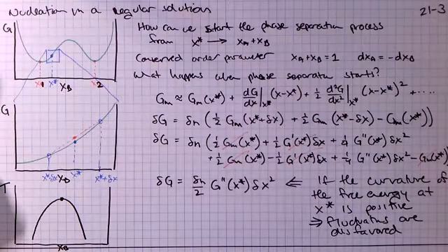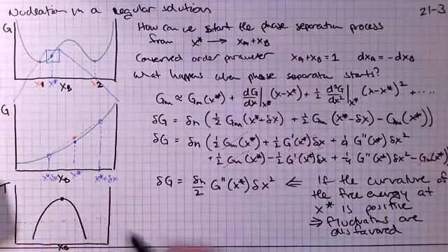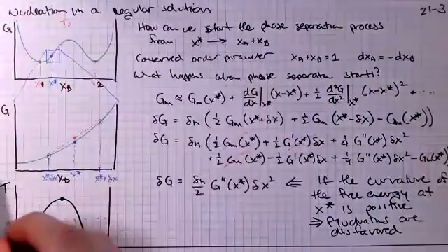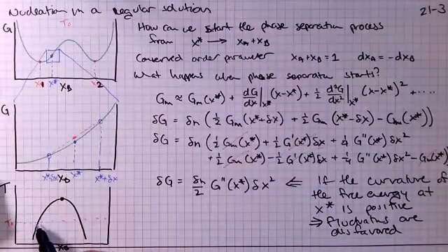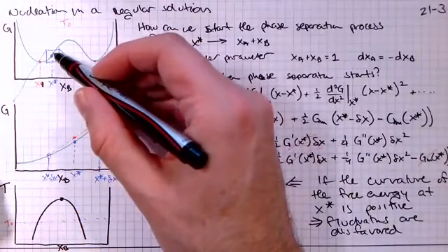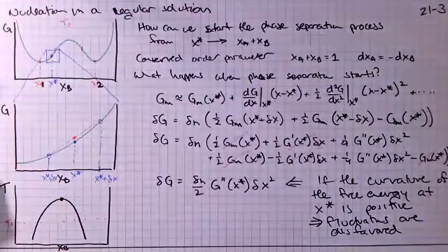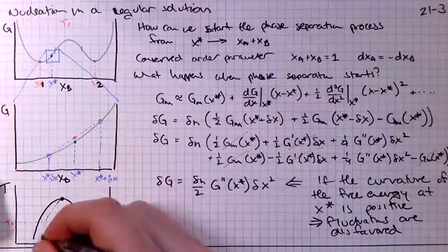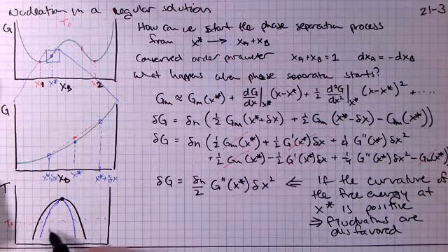But what we note is that if we're looking at one particular temperature below the critical temperature, let's say this particular temperature, T0, it's actually not until you get within the inflection point here that you can get spontaneous phase separation. So there's an inflection point here, and those correspond to points within the two-phase region.